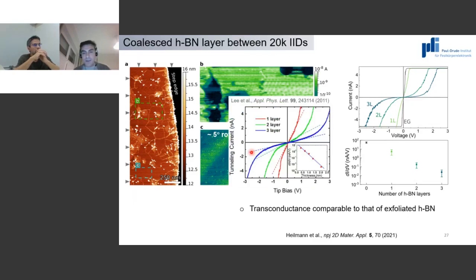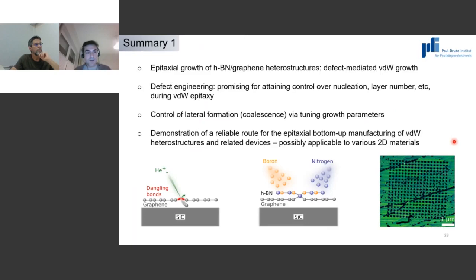Just finally comparing electrical properties here. So we estimated that by using conductive AFM for a different number of layers, and we get results that are very similar to exfoliated HBN, not on top of graphene, I guess, but directly transferred to an SiO2 substrate. But this shows that at least the grown material is not worse. It does not lose in quality in comparison to state-of-the-art flakes.